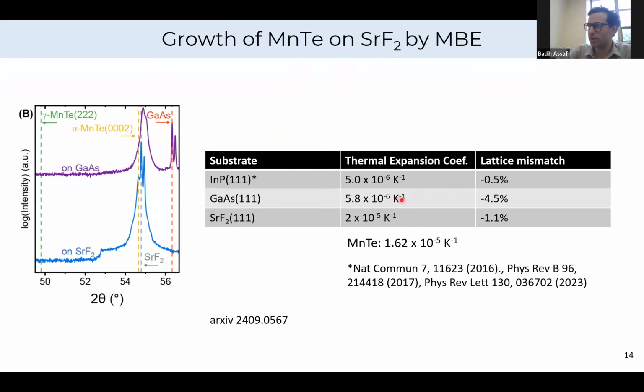So it's not surprising that when you grow it on indium phosphide and gallium arsenide, thermal strains are going to play a big role in dictating your properties. Strontium fluoride, on the other hand, also has a large thermal expansion coefficient. So it eliminates this thermal strain, essentially. Now, strontium difluoride has a slightly worse lattice match than indium phosphide, but turns out to be good enough to grow very good quality films.